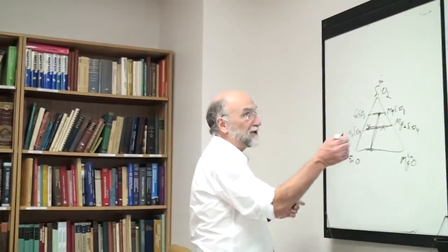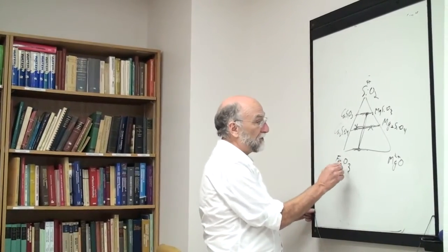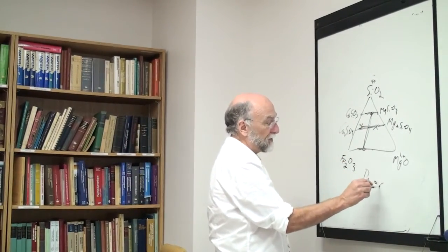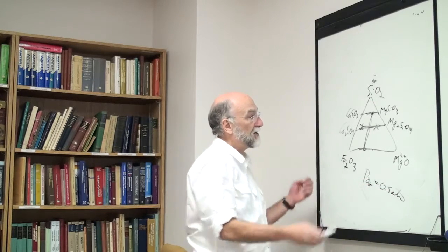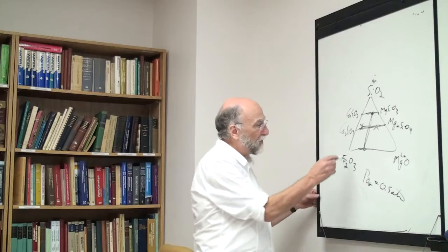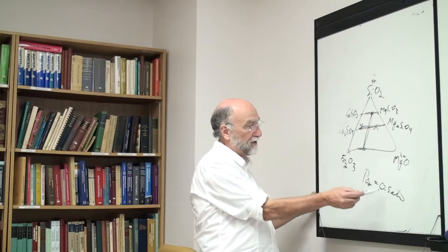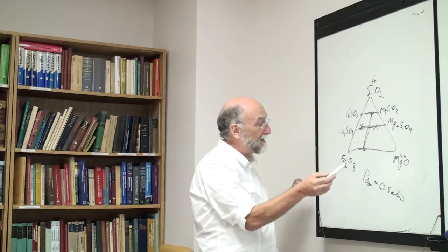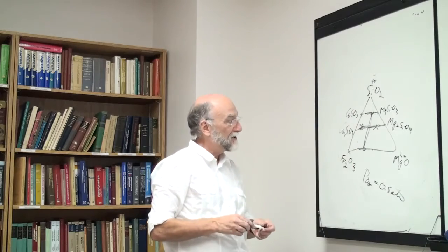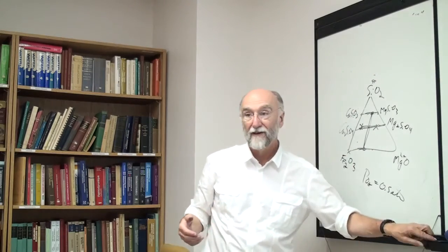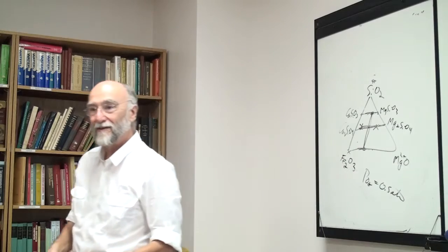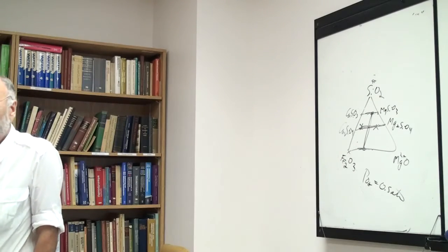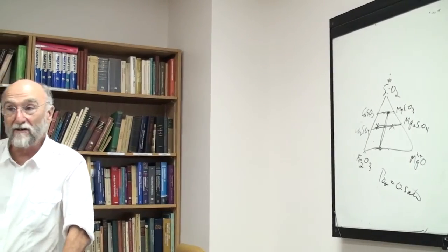You'll see this in the book, in the phase diagrams for ceramists. They'll plot the Fe2O3-MgO-SiO2 diagram at PO2 equals 0.5 atmospheres. They'll say, here it is, and there's your phase diagram. But what do they mean? You know this isn't Fe2O3, because if the PO2 is 0.5, you're going to have regions in which you have FeO. So what does it mean, the Fe2O3-silica-magnesia diagram when PO2 is 0.5 atmosphere? How do you interpret this thing? If I'm in a two-phase region, what does it mean? What phases is it? So I'll talk about that. This is one of the biggest problems, I think, with oxide diagrams: when you get the different oxidation states, people, when they're plotted wrong, misinterpret them, they don't understand.